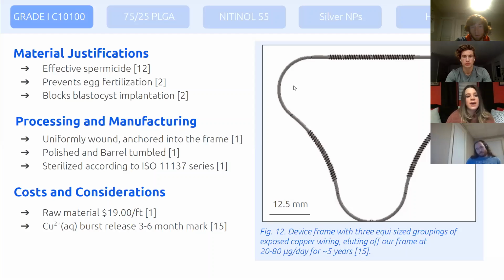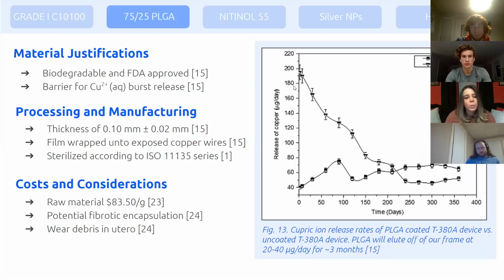The burst release effect of copper during the first 6 months of device lifespan is a significant deterrent. To address what burst release is and how our device will account for it, we look to a 2015 study which investigated such occurrences in vitro. The IUD working range requires cupric ion release between 20 to 80 micrograms a day, and the patient should not experience high bleeding and cramping relative to their baseline during this time. However, during the first 3 to 6 months after implantation, elution rates can be upwards of 200 micrograms.